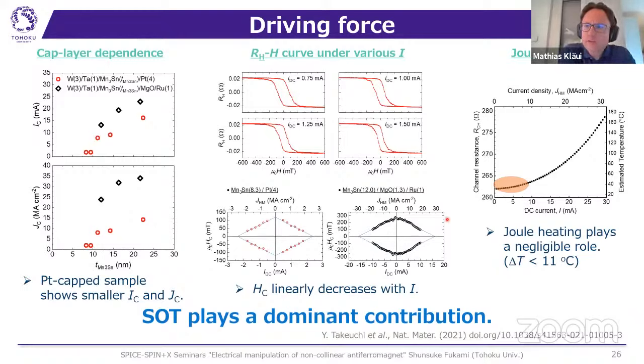Otherwise, just one final question. Can you talk us again through why you think that Joule heating is negligible in your experiment? What is the argument? Why is no Joule heating effect visible? We don't know, but if we apply a much larger current, the temperature goes up to a few tens of degrees Celsius, but the chiral spin rotation takes place at a current much below that. Of course, Joule heating exists. The change of resistance is just small, which means the change of temperature is small. Okay, good.